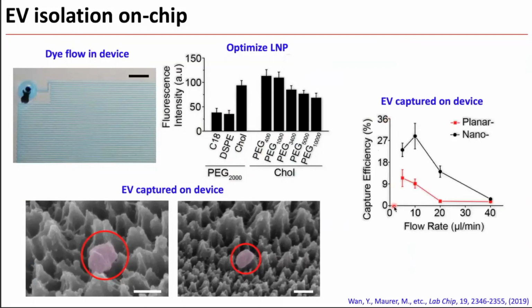We also optimized the flow rate versus capture efficiency. This is a continuous flow device. We have shown that the optimal capture efficiency is around 10 microliters per minute. At a lower flow rate, the mixing is not as efficient, so the vesicles do not really reach the surface. At a higher flow rate, the shear stress becomes higher, and also the interaction time between the vesicle and the surface is shortened. So that's the reason we have an optimized flow rate. And compared with a planar surface, the nanostructured surface has about 3 times higher capture efficiency.